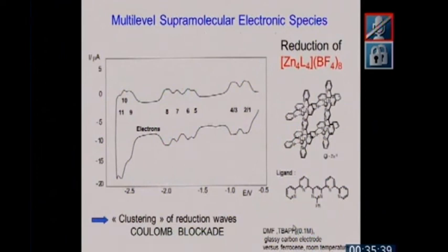To do a little bit of electrochemistry, this grid built on 4 zincs and 4 such ligands has redox properties shown by this cyclic voltammogram. What do you expect? You expect that as you reduce the system, introduce electrons, they should go first into the most easily reducible part, which is this pyrimidine here. So if you look at this compound now, you have first a set of 4 electrons, 1, 2, 3, 4. That means you first put an electron in here, then one in here, then one in here, and one in here. At this stage, the entity now contains 4 electrons. Each ligand contains an electron.